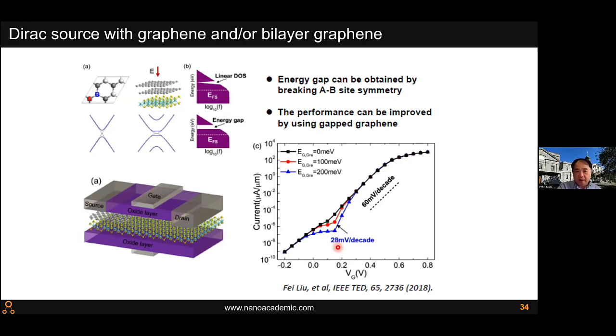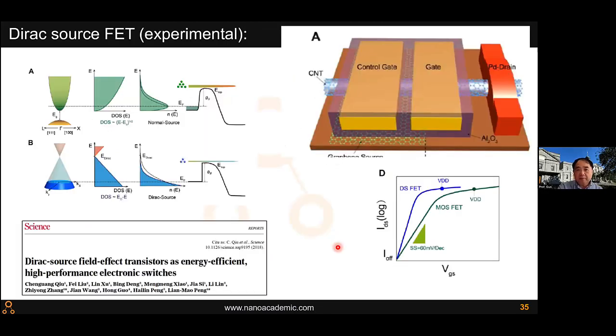This graphene can help us. Experimentally, my colleagues did this graphene transistor with the graphene here, and we did some theory. They use a nanotube as their channel, but the important thing is the source, which is the graphene. And indeed your density of states goes down, it cuts off your hot electrons. So it turns off your current much quicker compared with silicon or other heavily doped metal or something.